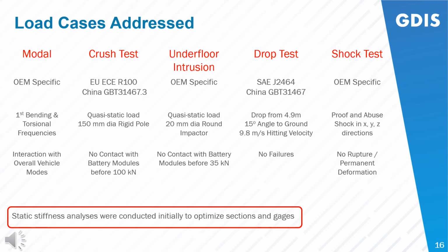There is the modal test, which is an assessment of the first bending and first torsional frequencies, and the criteria here is to avoid any interaction with any of the major vehicle modes. There is a crush test, which is application of a quasi-static load through a 150 millimeter diameter rigid pole to both the front and the side structures. The criteria is really no contact with battery modules before you can reach 100 kilonewtons.